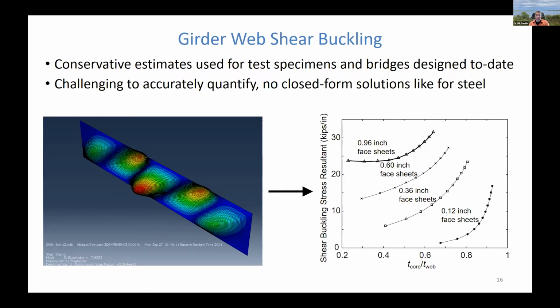We've run many, many simulations like this to develop figures like the one you see on the lower right, which is the shear buckling stress resultant in kips per inch. So that would be how many kips per inch a face sheet can take before it actually buckles. And for different ratios of the foam core thickness to web thickness. So that foam core to web thickness ratio is shown there. And we run this for a variety of different face sheet thicknesses: 0.12, 0.36, 0.6, 0.96. And this particular plot would be for one girder depth.